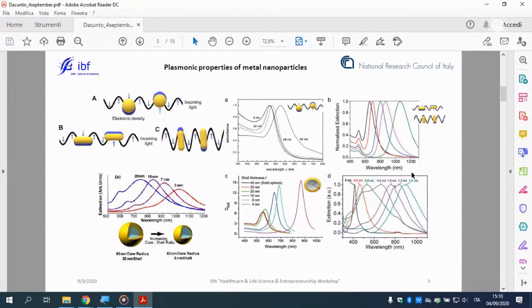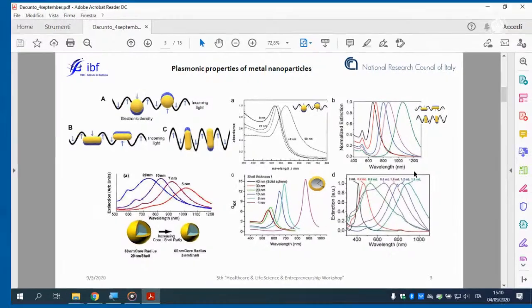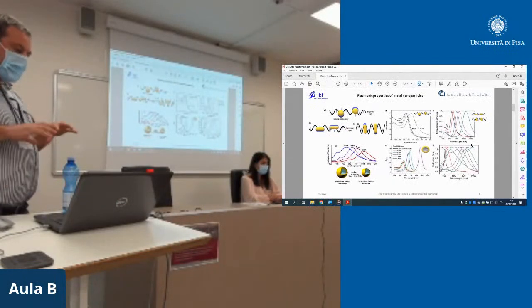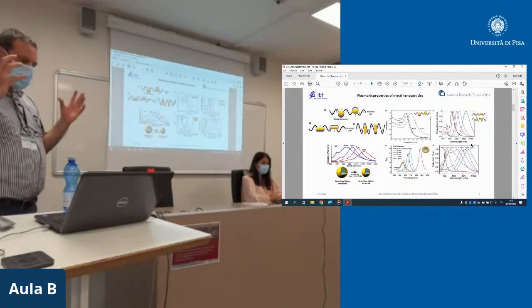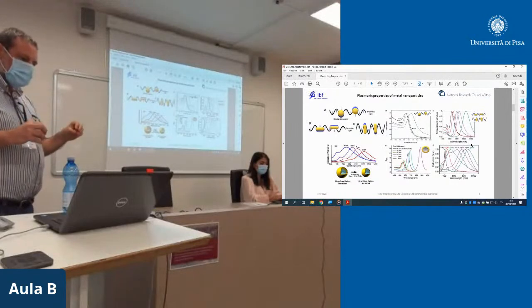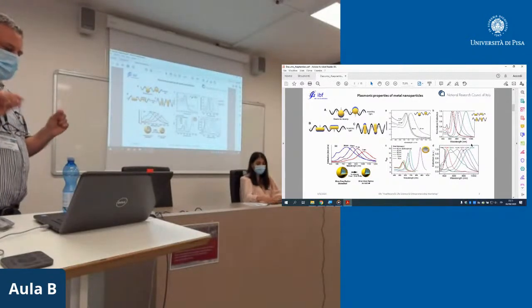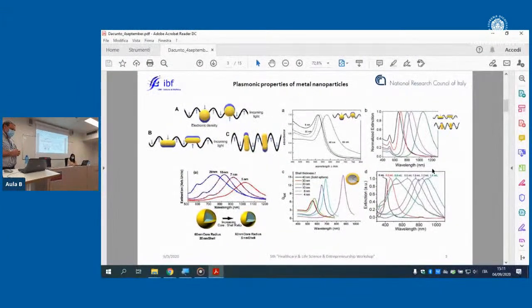Generally, metal nanoparticles like gold, silver, or copper, when illuminated with an electromagnetic wavelength, can generate an oscillation of electronic plasma, up and down inside the nanoparticles. By changing the dimension, the size and the shape of nanoparticles, spherical or nanorod, you can stimulate different modes. For example, between spherical or nanorod, or with nanoshell, a nanoparticle with a dielectric core and a thin gold shell, you can tune the plasmonic resonance depending on the illumination of your system.